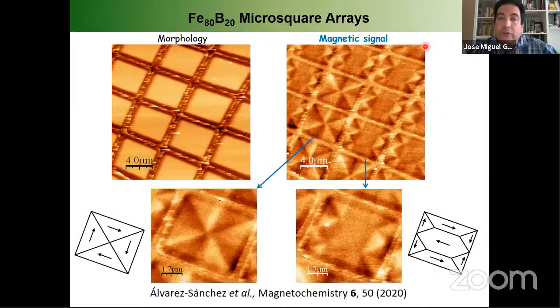Regarding the microsquare arrays, you can see on the left the topography, on the right the magnetic signal. Those squares, made of iron boron amorphous alloy, were developed to be used as sensors using the magneto-optical Kerr effect in the diffractive mode. With the MFM, we have checked that the magnetic domain state of this microsquare can exhibit 4 domains, like this one. This is the so-called Landau state, or 7 domains, the so-called diamond state. Those 2 states are minima in the energy landscape, and they are very close in value. So the remanent state of this square can be one or the other.